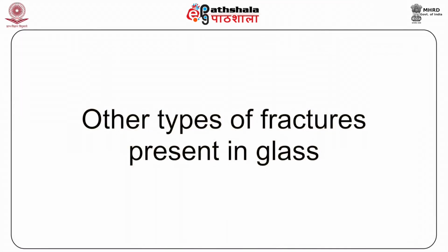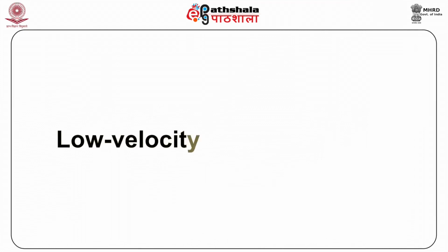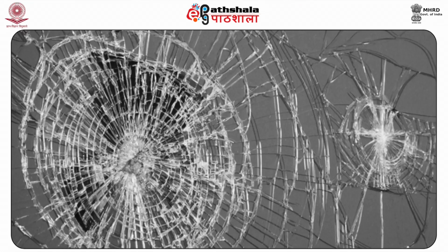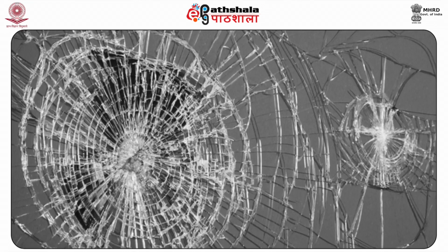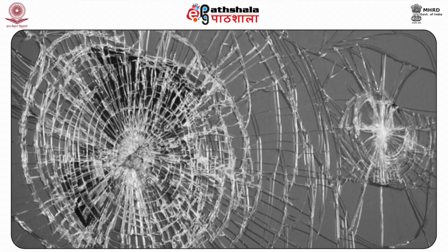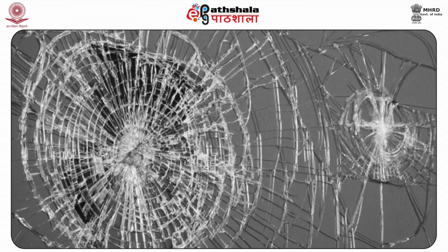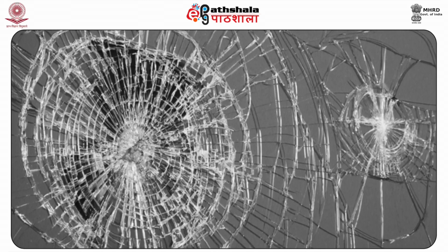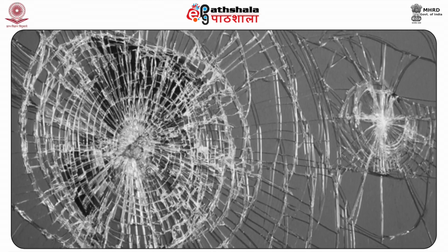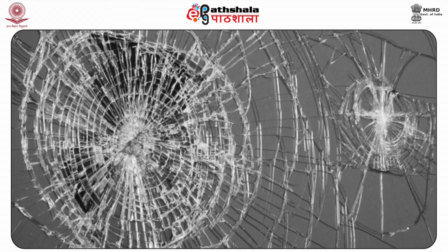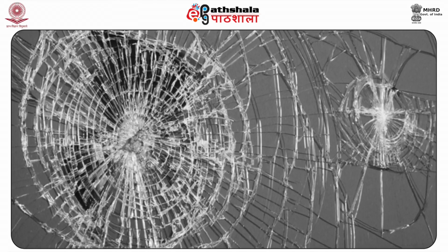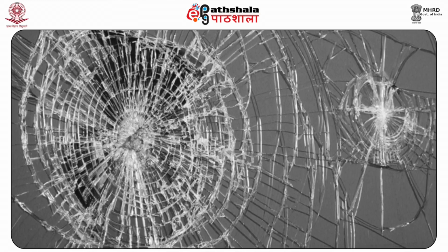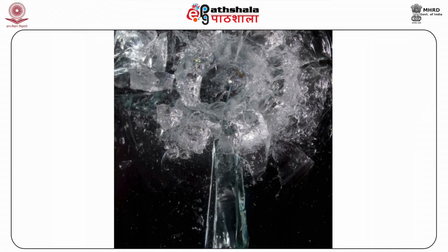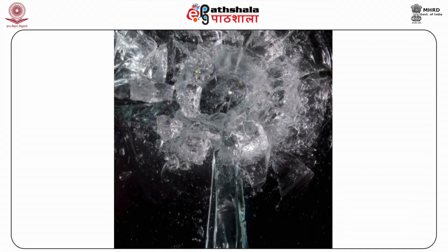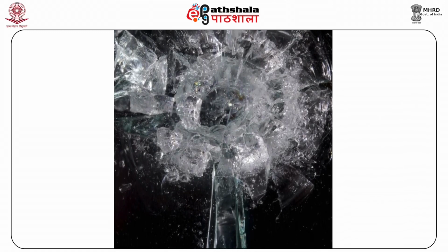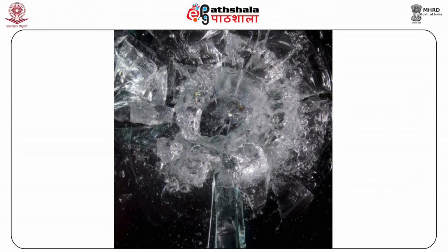Other types of fractures present in glass. Low velocity impact fractures. Low velocity projectiles produce cracks in the glass which radiate outwards from the point of impact: radial cracks. If a pane is firmly held on all sides, concentric cracks can form around the point of impact. The sequence of multiple impacts can be deduced when the cracks caused by a subsequent impact terminate at previously formed cracks.